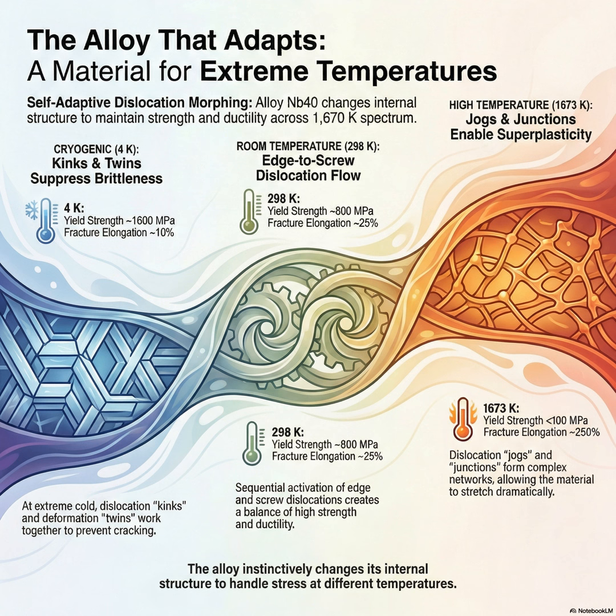So the fast ones go first to absorb the shock, then what? Then, as the strain builds up, the slower, more sturdy screw dislocations start to activate in sequence. These are the heavy lifters. And their activation makes the internal structure more and more complex.